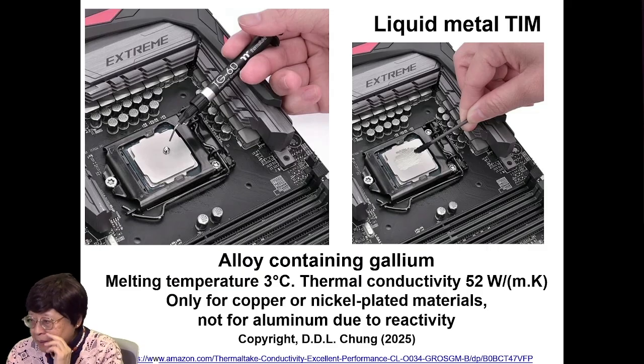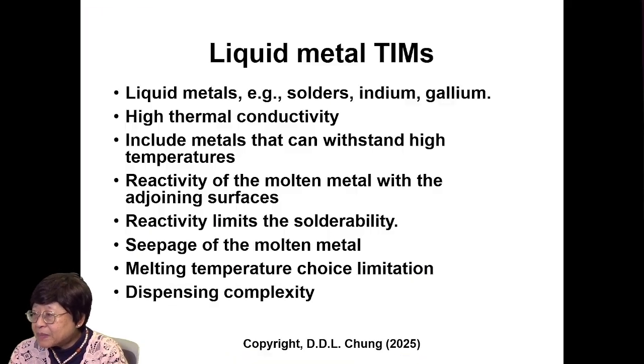Liquid metal TIM can be, say, an alloy containing gallium. In this example, the melting temperature is 3 degrees C, so it's a liquid at room temperature. The thermal conductivity is very high because it's a metal. However, it's only good for copper or nickel-plated materials, not good for aluminum due to the reactivity.